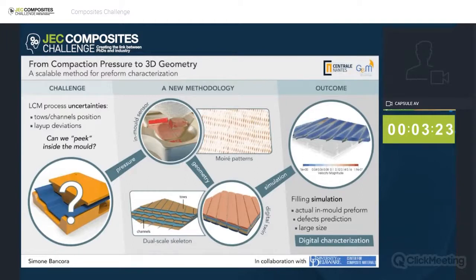I'll take you on a little journey, step by step, as represented on my slide, from the moment we place our material inside the preforming mold up to the moment we get some characterization by simulation. Our story begins with the flexible pressure-sensitive film. I have a sample right here with me. When layers are placed inside a preforming mold, we place this film on top of them, and it will capture the pressure field felt by the preform during the compaction.